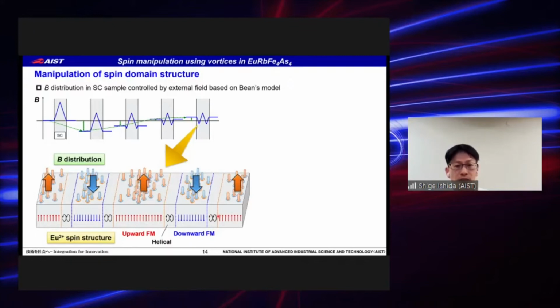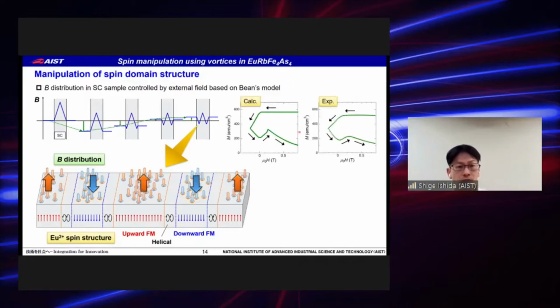Then we calculate the field dependence of magnetization. The calculated result becomes like this, with decreasing field and increasing field. And the right figure is the experimental result, which is in good agreement with the calculation results.